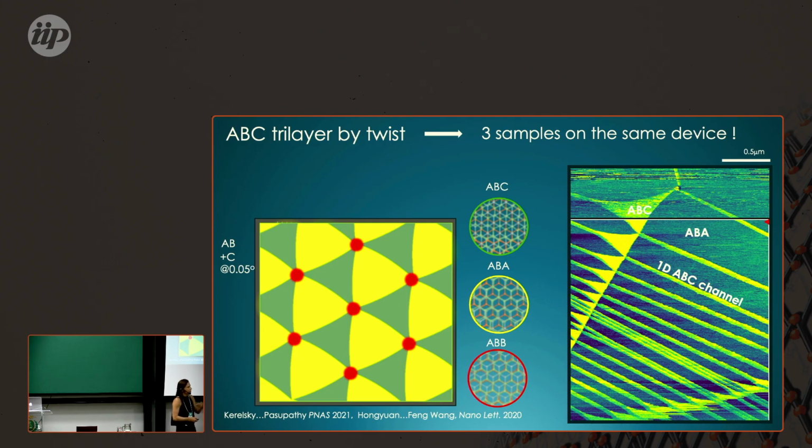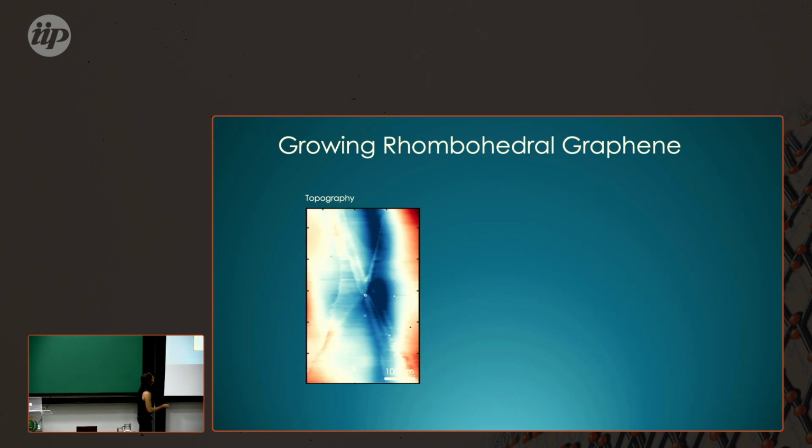However, we did a very thorough strain analysis, and we found out that inside this triangle, the sample is free of strain. It relaxes very rapidly, and the strain concentrates on these edges. And at the end, I'll get back, and we'll see the effect of strain on these one-dimensional channels.